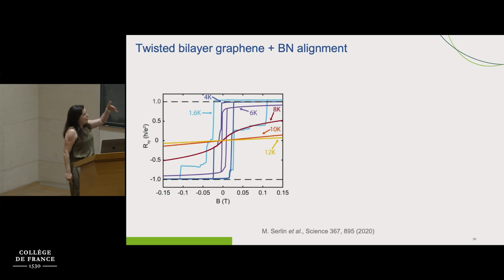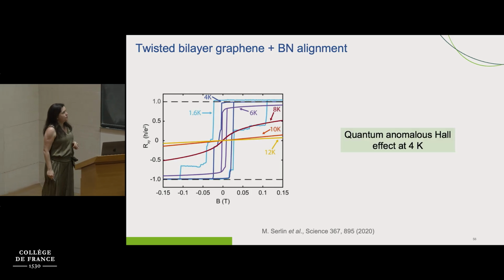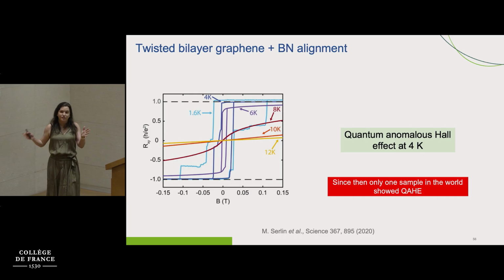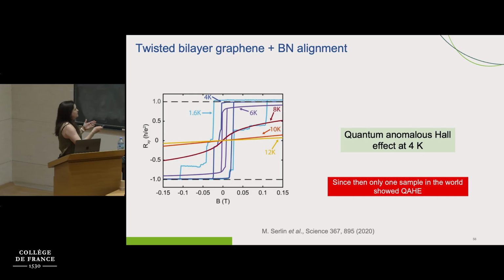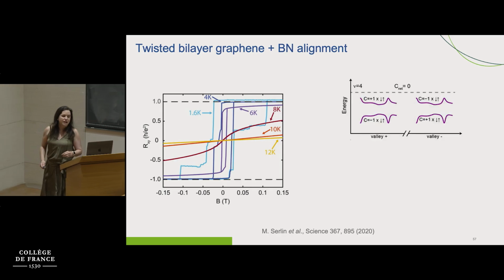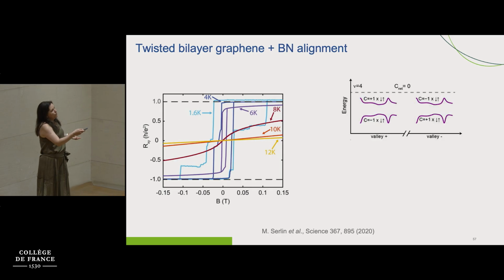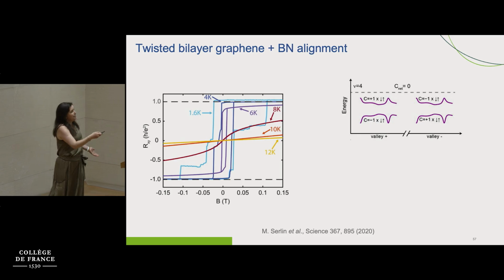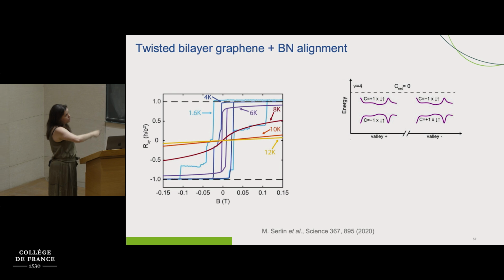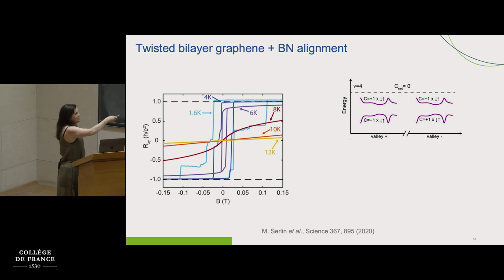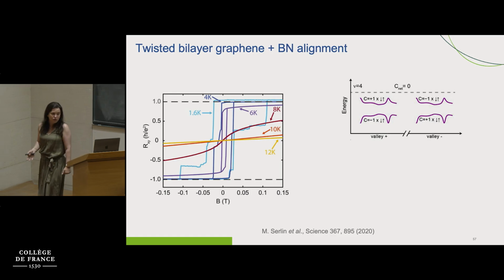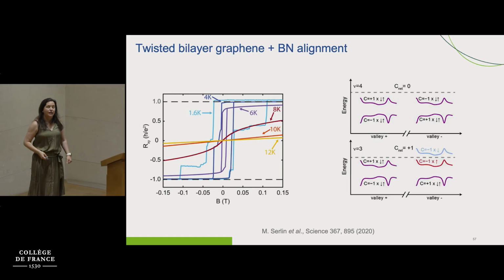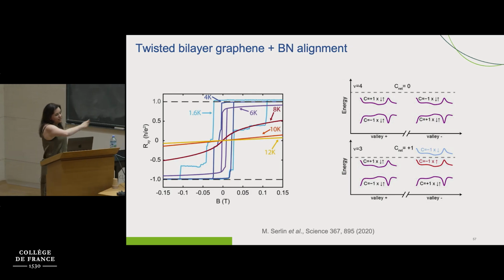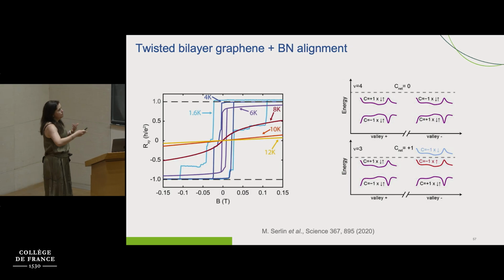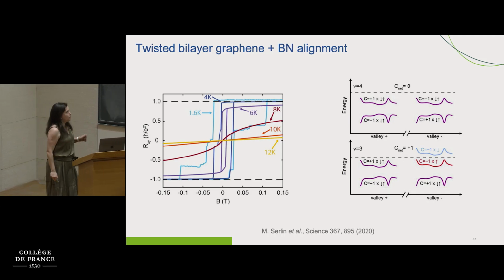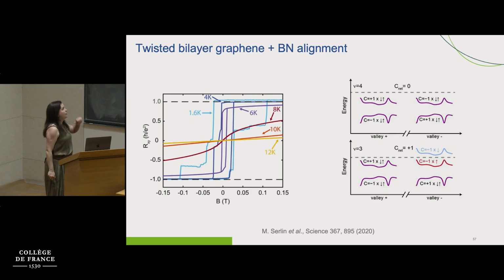These hysteresis loops tell you that there is an intrinsic magnetization of the system that is switching as you change the magnetic field. Okay? So the reason why we believe we observe this quantum anomalous Hall state, which, by the way, has only been observed in 1 sample in the world since 2020, is because when we have twisted bilayer graphene, we're going to have these topological bands, but you can see that the total Chern number is equal to 0, so we don't see any topological effects. Adding the boron nitride and breaking an extra symmetry is going to lift one of these degeneracies, and now your Chern number is going to change. And that's what makes possible the observation of this integer quantum Hall effect without a magnetic field, or the quantum anomalous Hall effect.